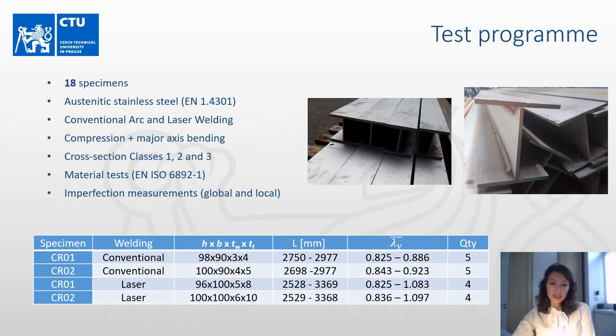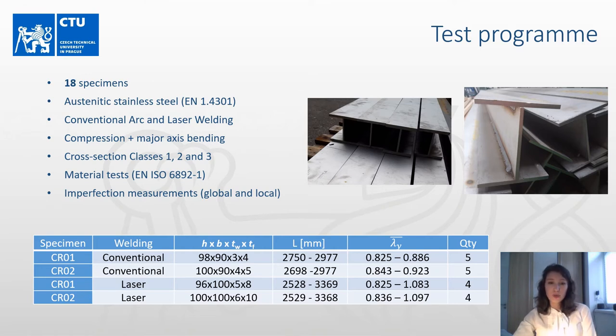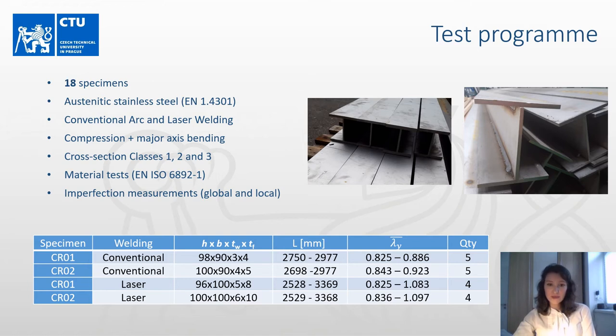My experimental study consists of testing 18 beam columns. All specimens were made of austenitic steel. Both conventional welded profiles and laser welded profiles were used. All specimens were loaded by compression with a range of initial loading eccentricities from pure compression to 60 mm eccentricities. The specimen geometry was chosen to cover cross-section classes 1, 2, and 3. Tensile coupon tests for every material and every plate thickness were performed following the procedure set out in standards, and additional geometric imperfections were also measured.